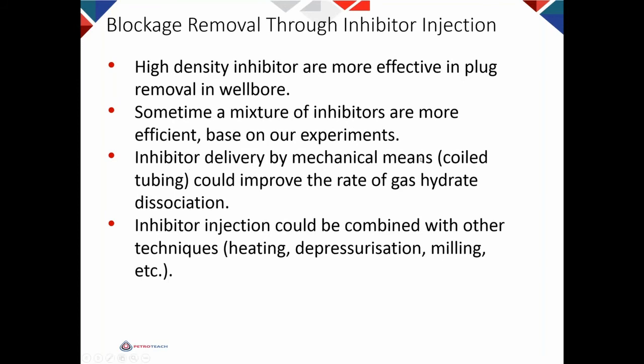Inhibitor delivery by mechanical means, like coiled tubing, can be more effective, especially if you combine it with heating, because even with inhibitor, you need to provide the heat. And that heat is either provided by reducing the pressure on the plug, or you provide active heat.